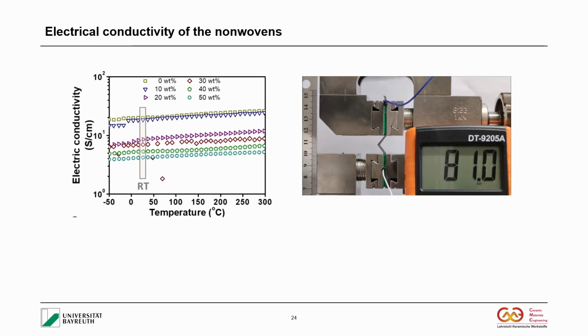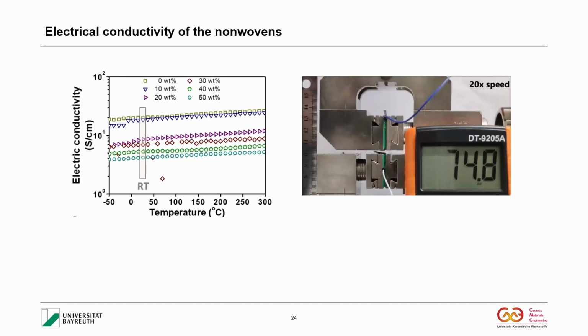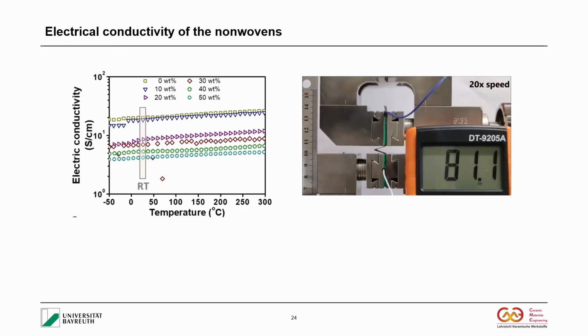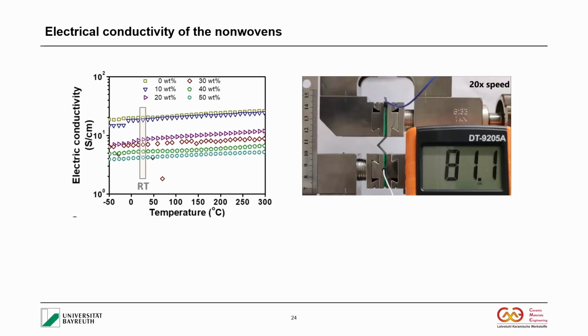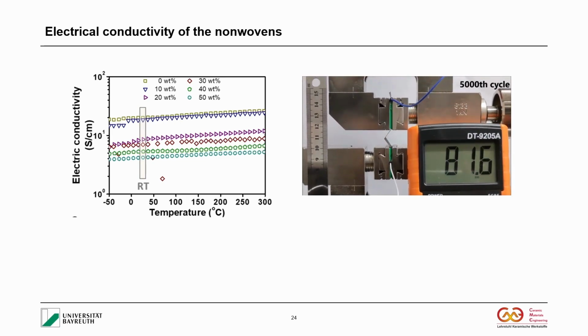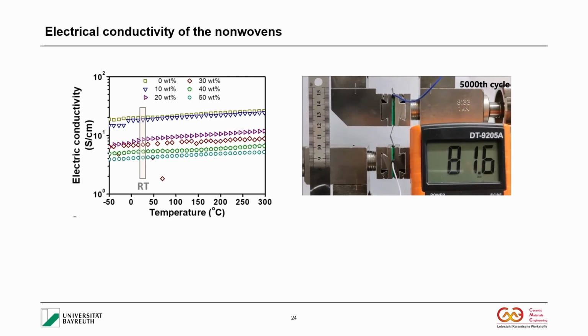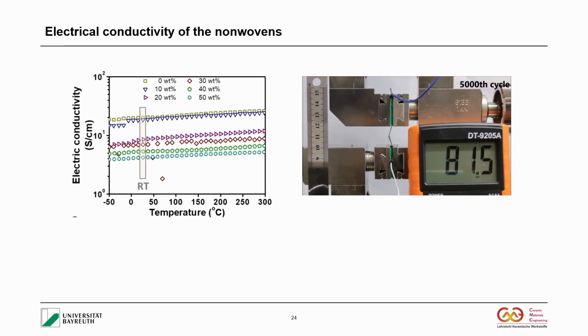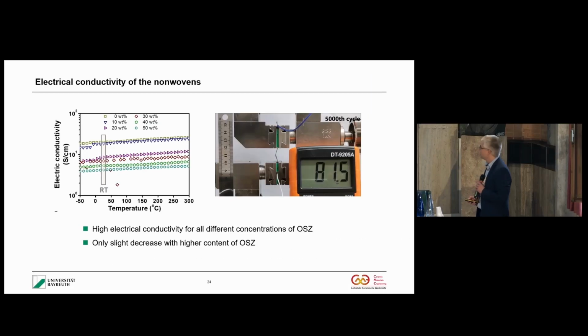So these experiments were collaborated at the chair of polymer engineering. And they have this kind of nice automatic machine. And we have to fold 5,000 times. So no PhD student was involved, at least it was not his job to do it 5,000 times. And actually you see that the electrical resistivity was not changing a lot, even after 5,000 cycles of bending. And it's very interesting that the fibers are foldable, and the electrical conductivity is not changing a lot.